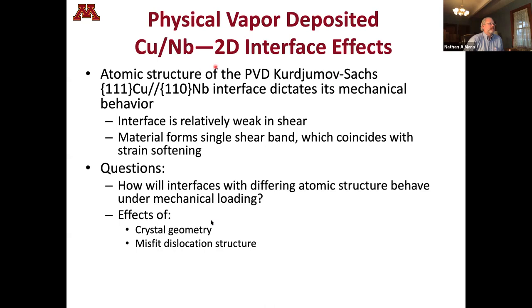So if we move to just wrap up what we found here, what we found is that the atomic structure of this particular type of interface dictates its mechanical behavior. The interface is weak in shear, as I mentioned. We form this single shear band, which coincides with strain softening. So you can imagine we rotate the layers, they start to shear, the material is weak in shear, so you see the softening effect. But it brings up other questions. What happens if we start messing with this atomic structure? What happens under mechanical loading?